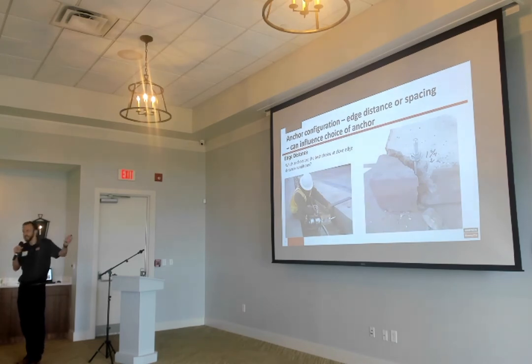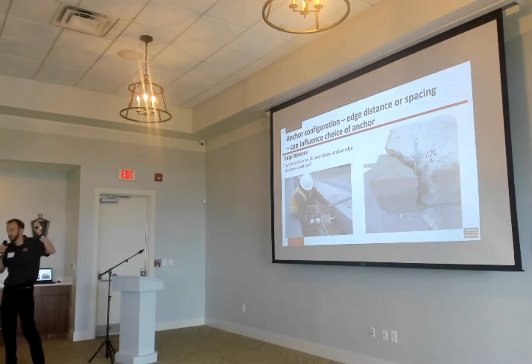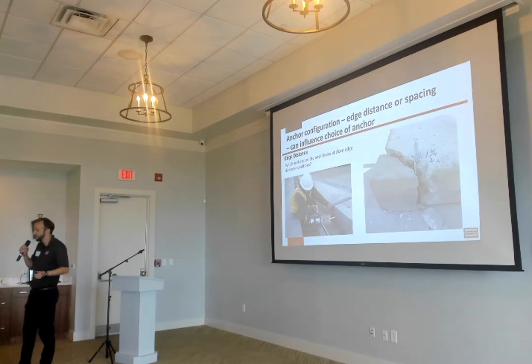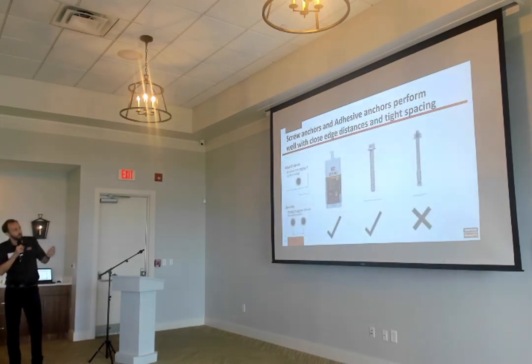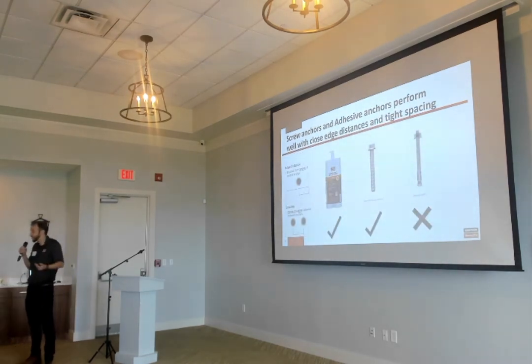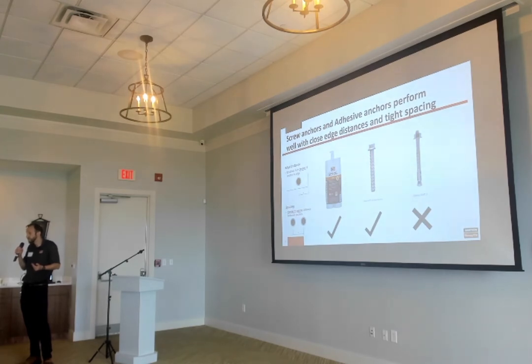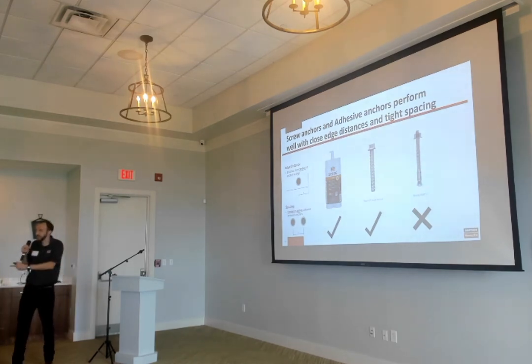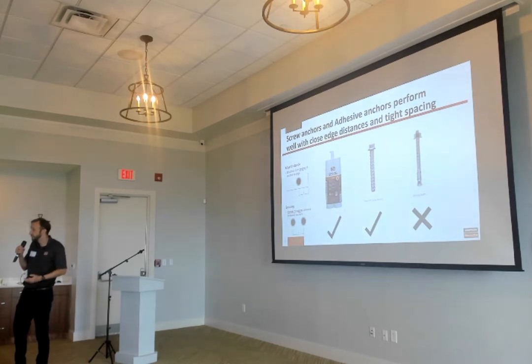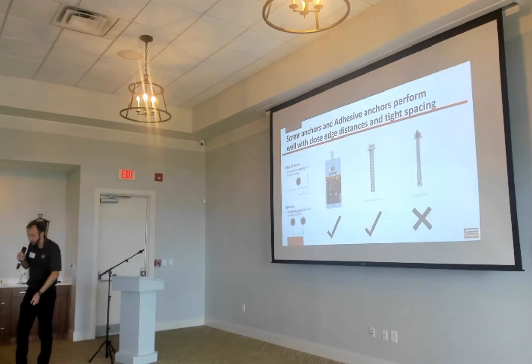All right, also edge distance. Like I said, the screw anchors and adhesive anchors perform very well when you get close to the edge, and you can actually get them close to the edge. For the expansion anchors, you can't get them close to the edge. It's upwards of 4.5 inches minimum edge distance. So if you're using this expansion anchor on a seal plate that's right along the edge, you're encroaching past that minimum that we set, and that is installed incorrectly. What could occur is if you tighten it to the appropriate torque, you might just get a blowout during the installation process on the side of the concrete.